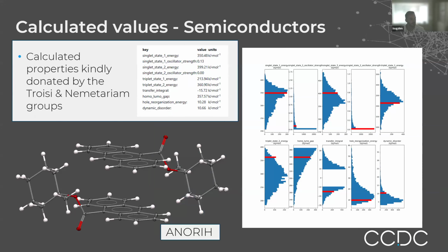We've also recently performed a project in collaboration with Alessandro Troisi and Tahere Nematiaram. So the work was done at Liverpool when Tahere was there for her PhD and postdoc. So this is a data set that was calculated for structures within the CSD. The molecules were extracted from their crystal structures, and then semiconductor relevant properties were calculated using DFT methods. There's a set of papers to go into more detail of the methods that we used. It's quite high-end calculations.